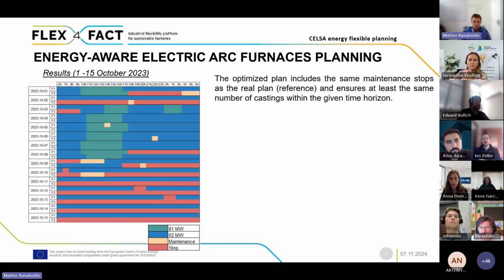Now we can see the results in a 15-day period between the 1st and the 15th of October 2023. What we see here is basically the results of this optimization model, where we see in each hour for furnace 1 and furnace 2 which is the operation that needs to be taken. In green we see the high power mode, in blue the low power mode, in yellow the maintenance, and in red the stops.